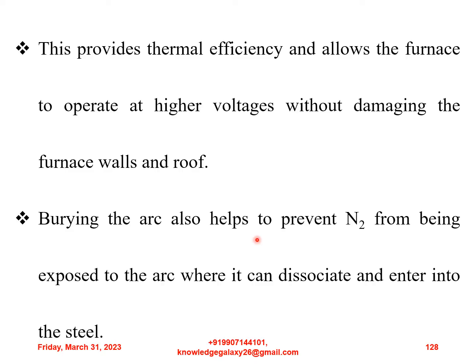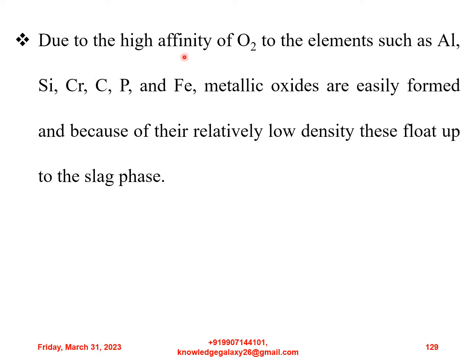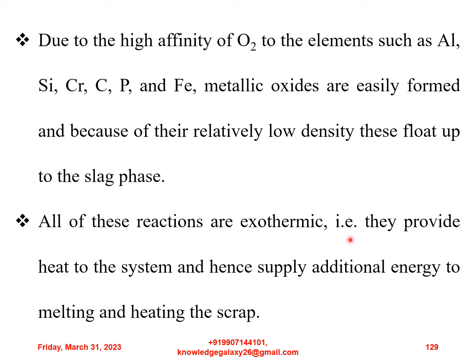Burying the arc also helps to prevent nitrogen from being exposed to the arc where it can dissociate and enter into the steel. Due to the high affinity of oxygen to the elements such as aluminium, silicon, chromium, carbon, phosphorus and iron, metallic oxides are easily formed, and because of their relatively low density, these float up to the slag phase. All of these reactions are exothermic, that is, they provide heat to the system and hence supply additional energy to melting and heating the scrap.